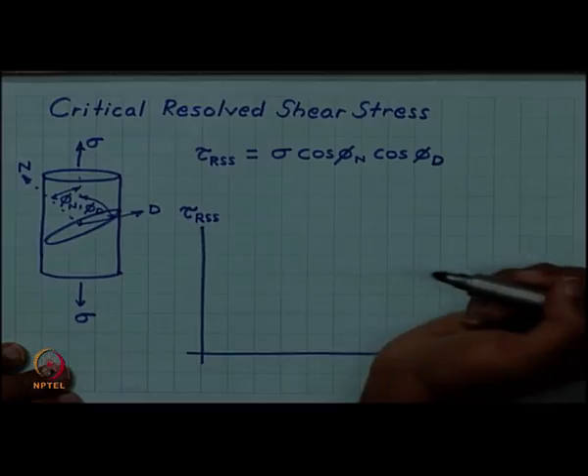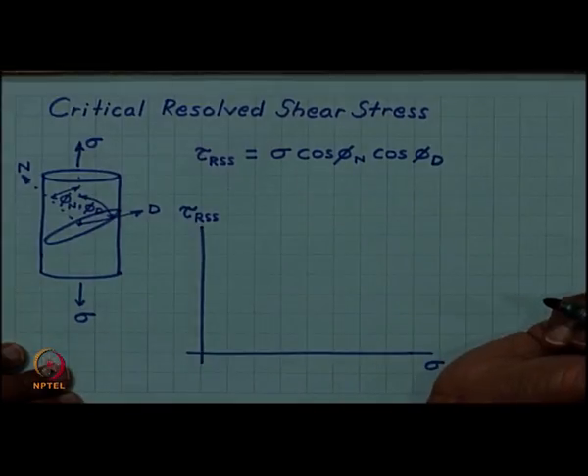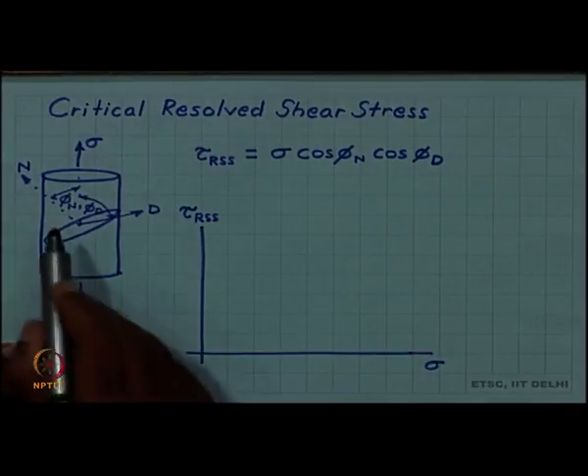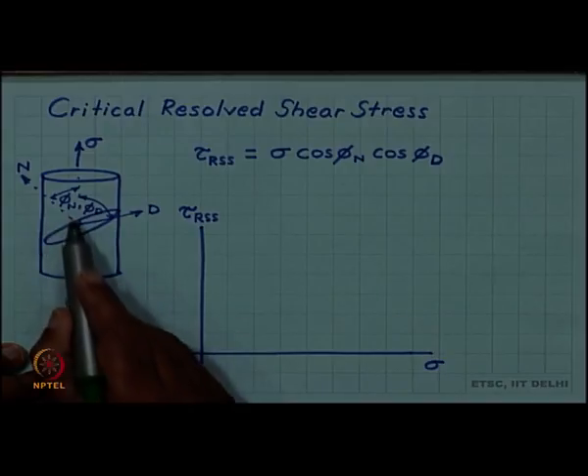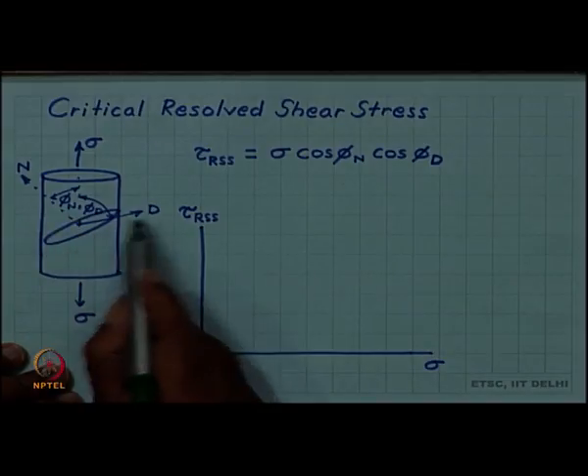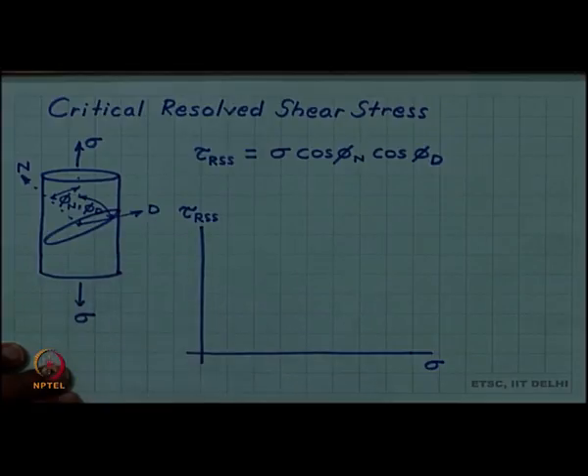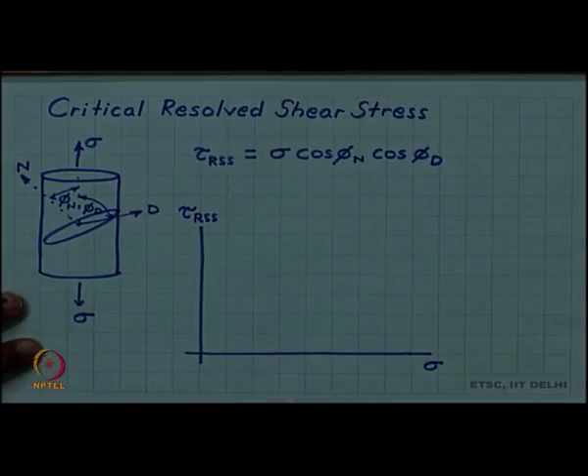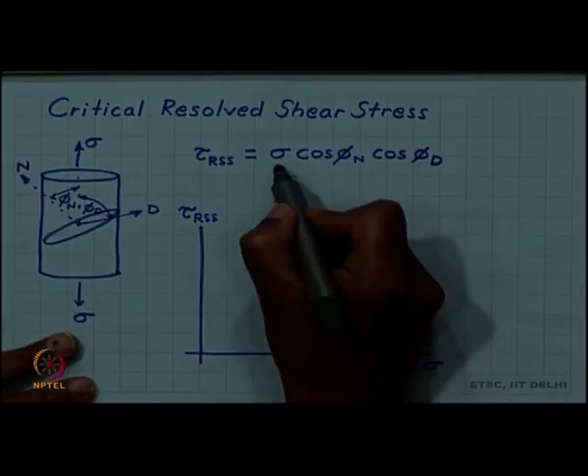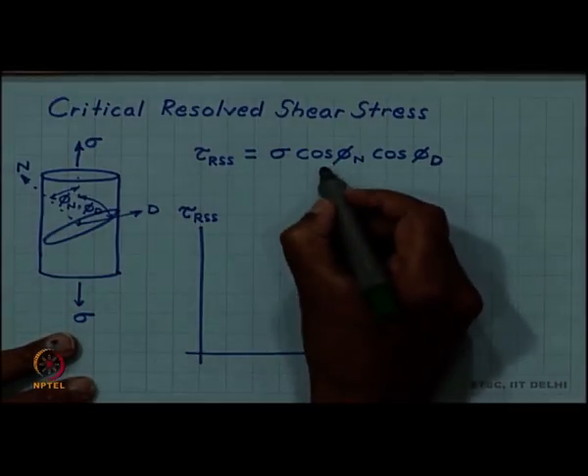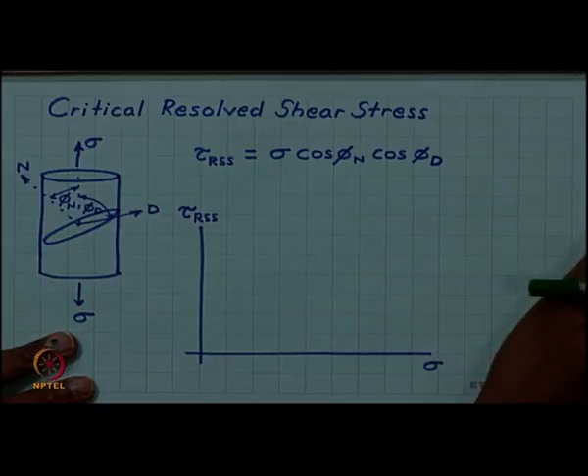Suppose we are loading a sample in uniaxial tension. We have seen that on a slip plane which is inclined at an angle phi n and a slip direction which is inclined at an angle phi d, there is a resolved shear stress acting on the material which is given by the applied tensile stress times cos phi n cos phi d.